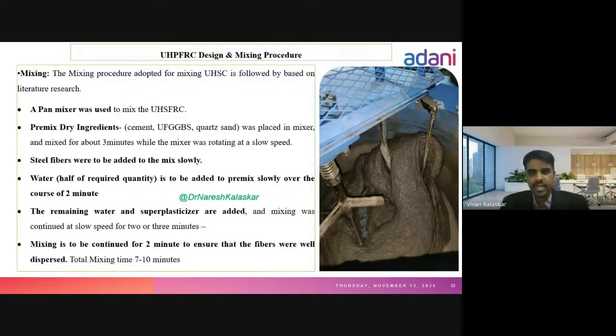After mixing 3 minutes, you have to add the admixture slowly. You should not add the admixture totally at one time. You have to see how the mix is behaving when you are adding the admixture. It is a total 7 to 10 minute procedure. When you are adding water, simultaneously you have to add steel fibers also.